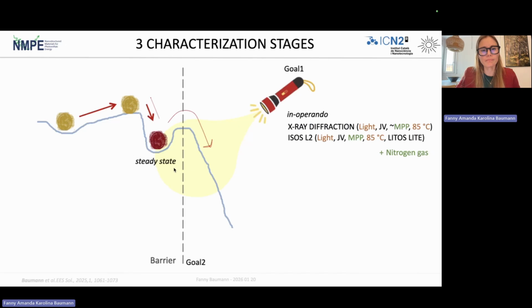So if we imagine the stability experiment something like this, we produce our solar cell, the perovskite is in a steady state, and we would like it to stay there. Eventually something is going to happen, and we're going to go beyond this point of no return and reach towards a more degraded state. So what we're trying to do is we're going to try to provoke these changes by using rather harsh conditions, and we are going to do two parallel experiments with in-operando characterization.